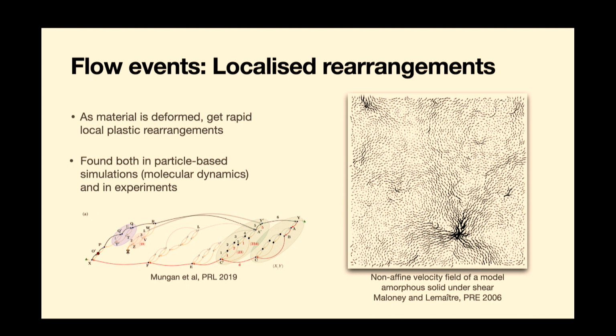under shear, for example, and this has been well established in steady shear, that the flow takes place via rapid local rearrangements, which are plastic in the sense that they're typically irreversible when you go backwards, and these then cause strain fields around these. This is a snapshot of a displacement field around one of these plastic events, okay? And you can actually resolve, there have been some nice papers, exactly how the system transitions through these various plastic elements through its states in configuration space. So this is something that you can also see experimentally, but also, of course, in simulations.